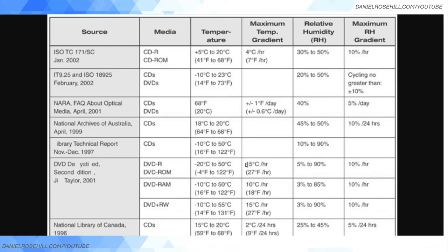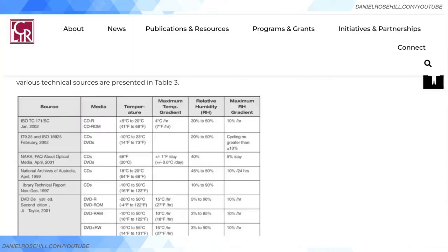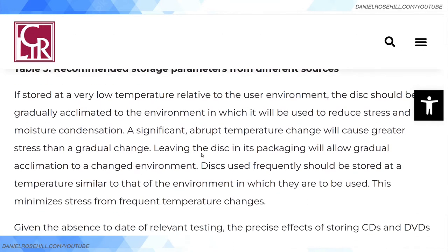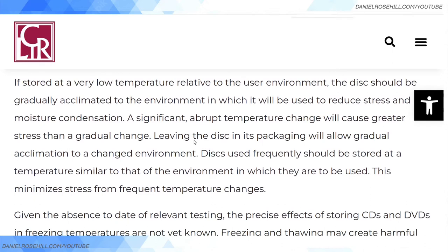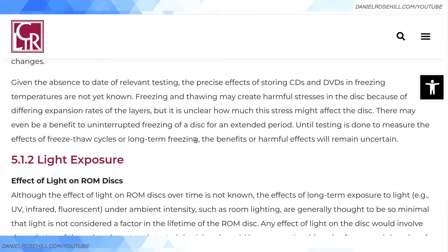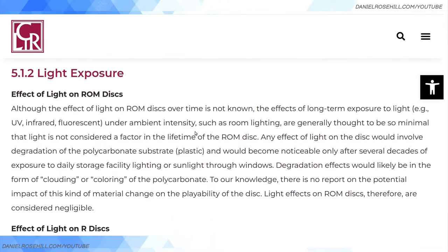The key takeaway for M-Disc users: try to put your M-Discs somewhere cool that doesn't get above about 30 degrees, and where temperature and humidity don't yo-yo dramatically during the day. Find somewhere stable within that fairly big range and you should be fine. Also, if storing at a very low temperature relative to the environment, discs should be gradually warmed before use.